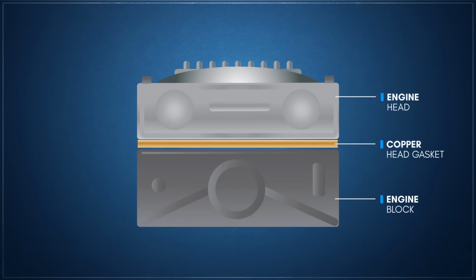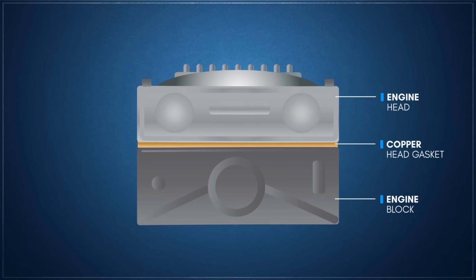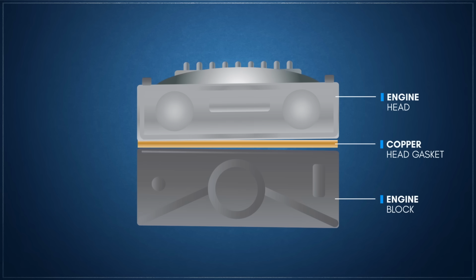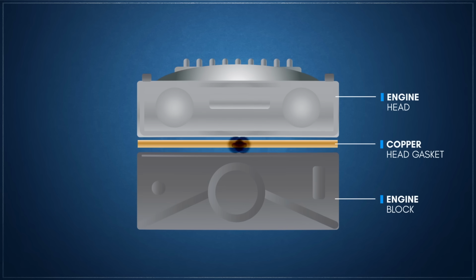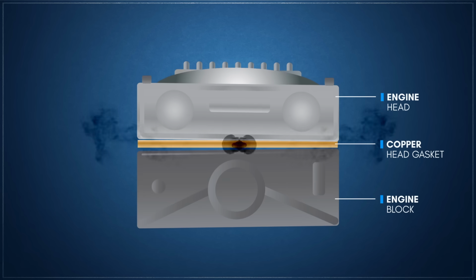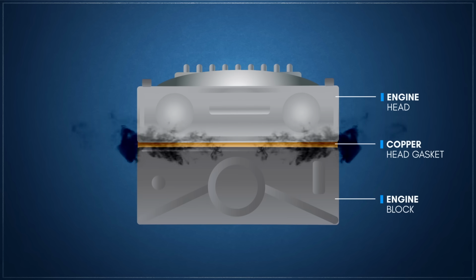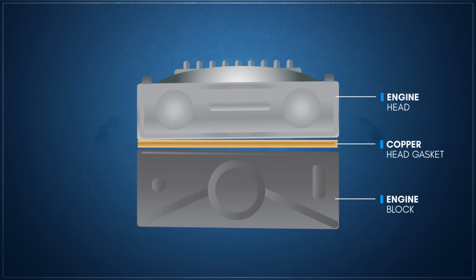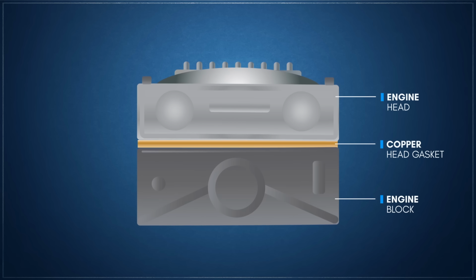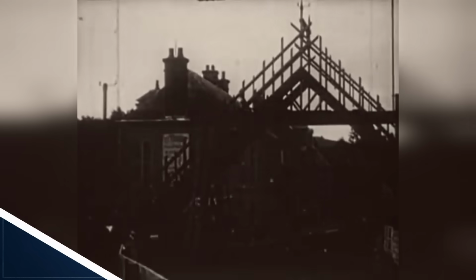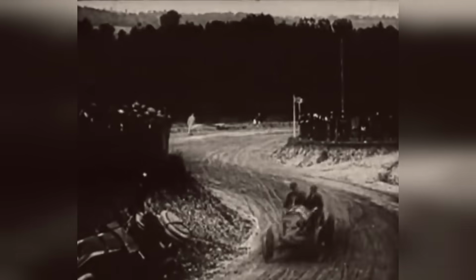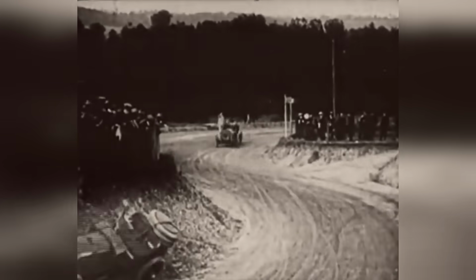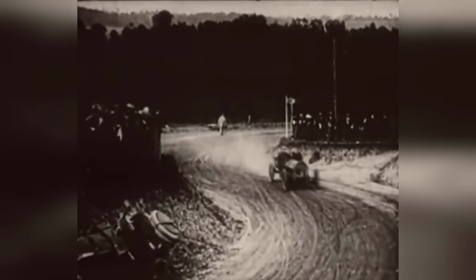As both the copper gasket and the engine components experienced heat cycling and combustion stresses, their relative motion would create inconsistencies in the clamping force along the gasket's surface. This allowed combustion gases and liquids to eventually seep through. While regular retorquing of the head bolts could reestablish the seal, these early head gaskets remained unreliable. This was such a problem that in the early days of motorsports, head gasket failure was the most common reason for race cars to not finish a race. Oil leakage was so prevalent at race events that it was not uncommon for sand to be applied to the racetrack.